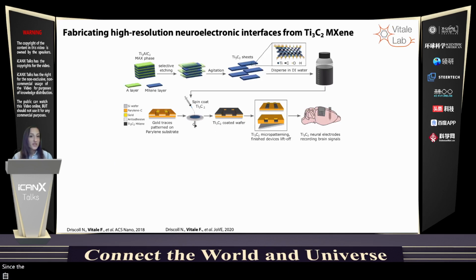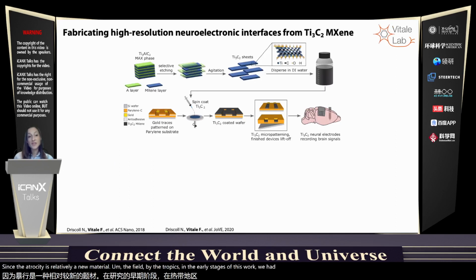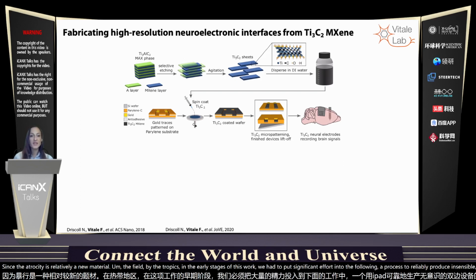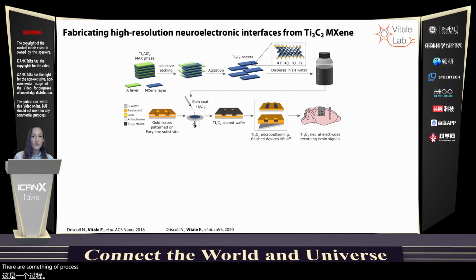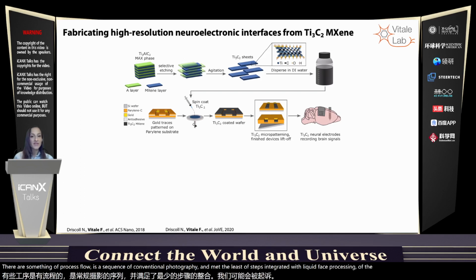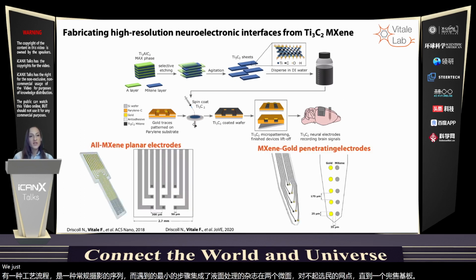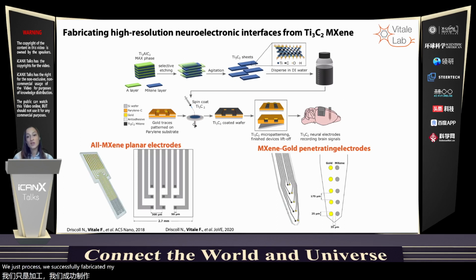Since Ti3C2 is relatively a new material in the field of bioelectronics, in the early stages of this work, we had to put significant effort into developing a process to reliably produce implantable bioelectronic devices with MXene. The resulting process flow is a sequence of conventional photolithography and metal lift-off steps integrated with liquid phase processing of the MXene ink to micropattern the electrode sites, in this case, onto a parylene substrate. With this process, we successfully fabricated microelectrode arrays with different geometry.